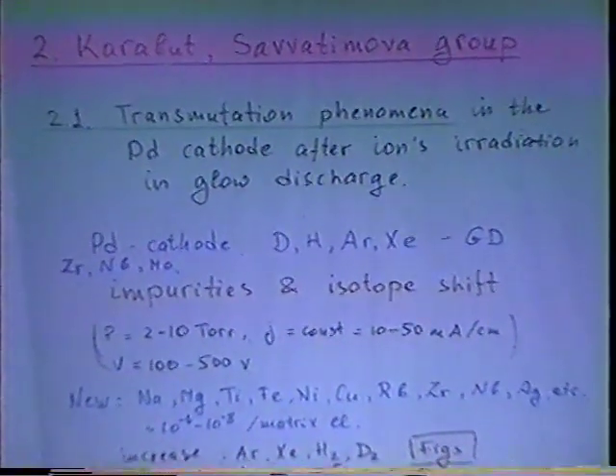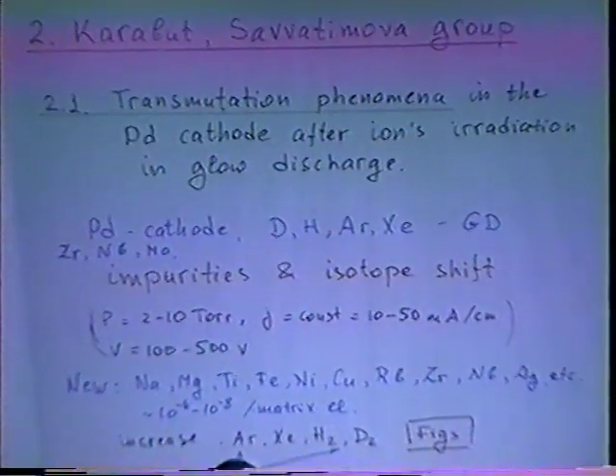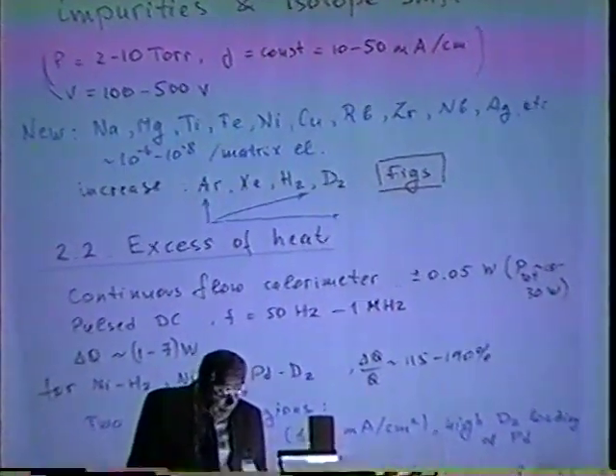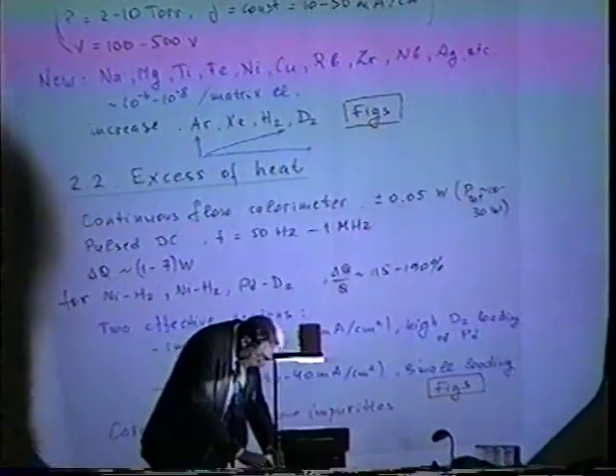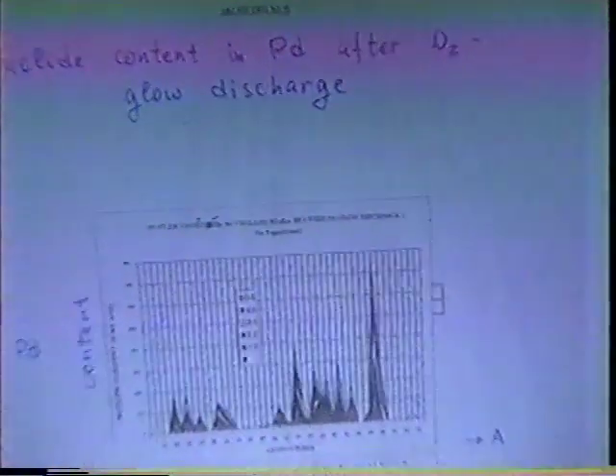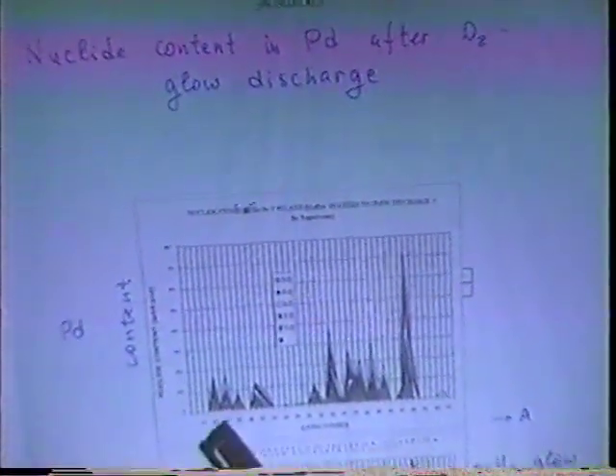The other group from the same institute, Karabut, Savvatimova, and Tada, continued to study transmutation phenomena in palladium cathode after irradiation by ions in glow discharge. For the cathode, they used various materials, and for gas, they also used deuterium, hydrogen, argon, and xenon. And they observed both impurities and isotopic shift in their samples. Here you can see some parameters of their work, and they observed a lot of various new elements. And here you can see the results. This is the nuclide content in palladium after glow discharge. And here is atomic number and content. You can see many elements.